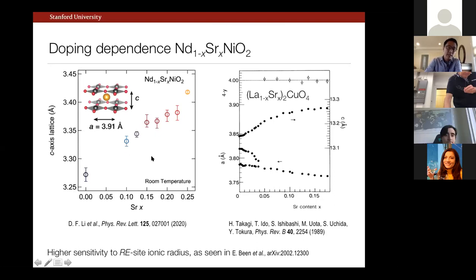I will contrast our doping studies with the canonical 214 cuprate system, the work of H. Takagi. And you can see that qualitatively there are similarities in terms of having an expanded C-axis lattice parameter. I should say, though, that the sensitivity is much, much higher, meaning this variation is about a factor of 5 or more larger. This has been seen in electronic structure calculations as a function of rare earth site. In this case, the simple-minded way to say it is that the strontium ionic radius is rather larger than the neodymium, so you would expect an expansion.